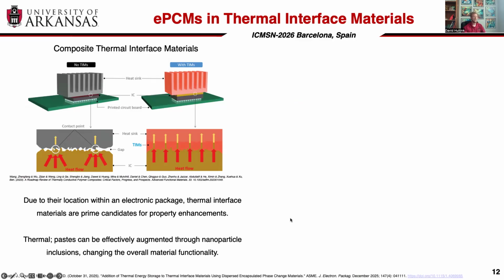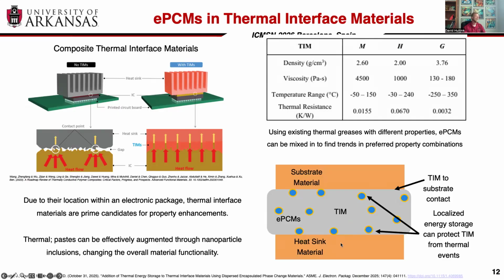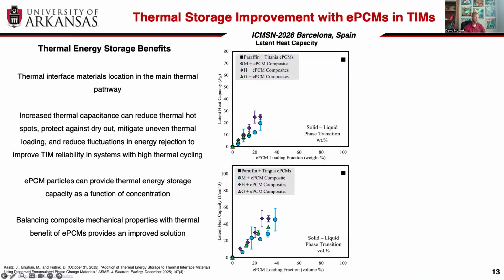But this also provides opportunity of integrating these ePCM materials for adding thermal capacitance locally near the heat generating area so that we can smooth out any transient temperature spikes on the device as well. So we looked at three different TIM materials, and added these ePCMs into the system to look at the thermal capacitance addition that we can achieve.